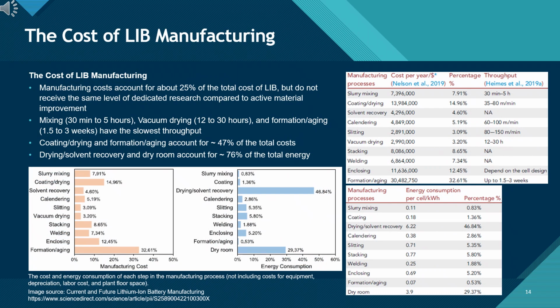The cost of LIB manufacturing. Battery manufacturing contributes roughly 1/4 of the total cost of a lithium-ion cell. Interestingly, despite this large cost share, manufacturing processes still receive far less R&D attention compared with active material development. Among all steps, mixing, vacuum drying, and especially formation/aging have the slowest throughput, ranging from hours to several weeks. This slow pace directly increases both operational time and overall facility cost.